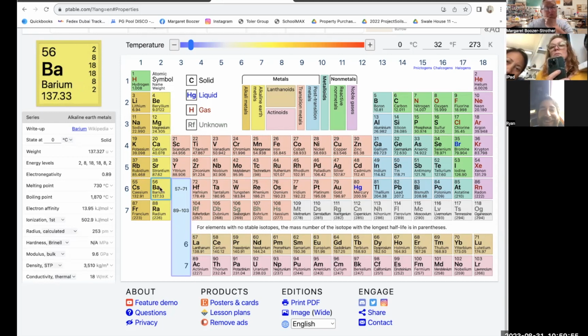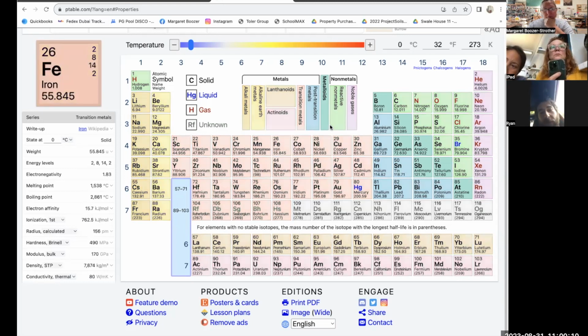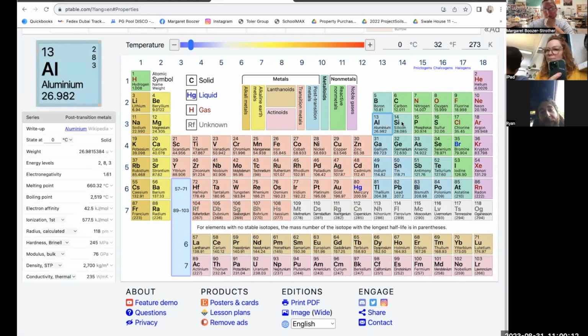Yeah, so then there's a couple of other ratios that we really care about. We want to make sure that our silica to alumina ratio is under 12 to 1 or so, around there. It can be a little bit over, but not too far over. And if we're talking about cone 6, we're going to have a couple more ratios that we care about. But for the most part, the silica to alumina and the alkali to alkaline earth flux ratios are really important.